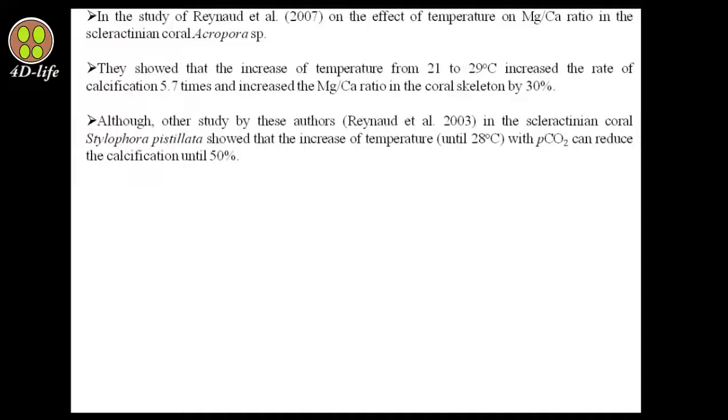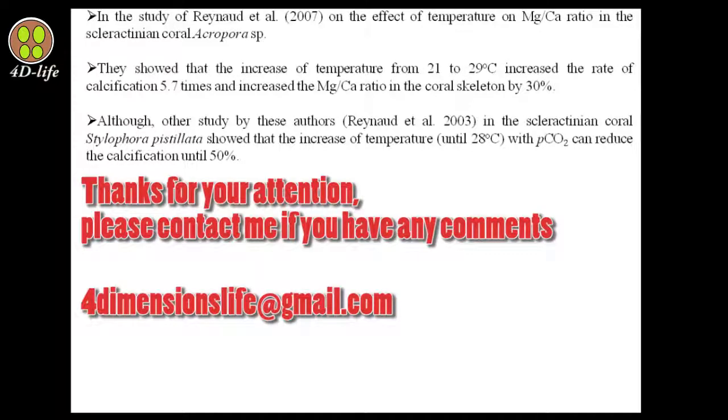Although another study by this author in 2003 on the scleractinian coral Stylophora pistillata showed that an increase of temperature up to 28 centigrade with a high amount of PCO2 can reduce calcification by up to 50%.